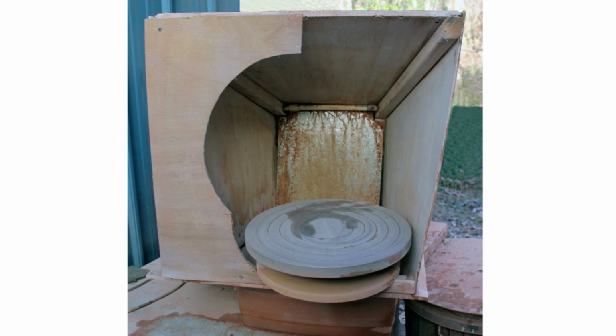I periodically clean out that bucket and save all the glaze waste. When I have a sufficient amount, I mix it up to a typical glaze consistency and test it on a broken shard and observe it. After observing one glaze shard, I guesstimated that it needed EPK and added it in to control the flow of the glaze.